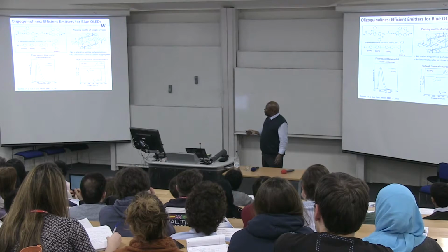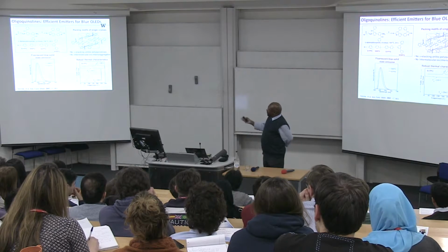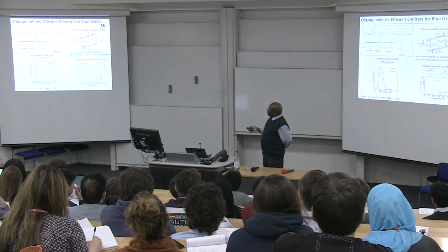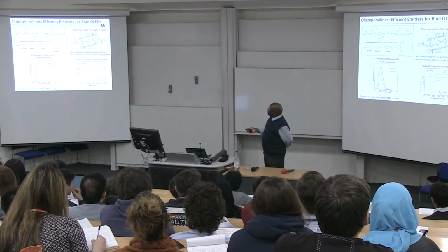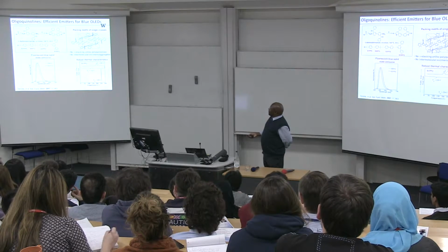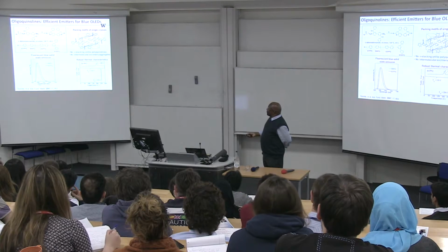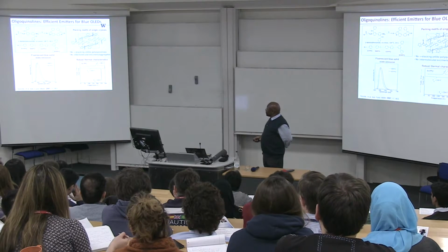One of the reasons why it was very difficult making efficient blue LEDs was the difficulty in materials degrading over time, or if they crystallize or pack very efficiently, that leads to new electronic states that can emit colors more reddish compared to the blue that you are interested in. However, these particular oligoquinolines, as you can see here, emit very nicely in the blue region.